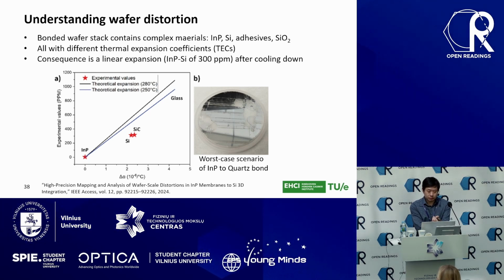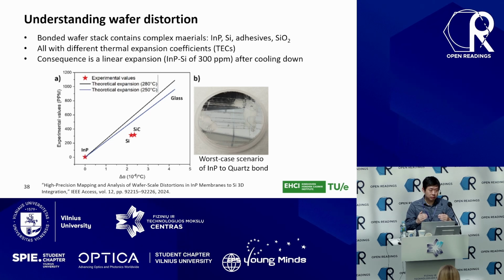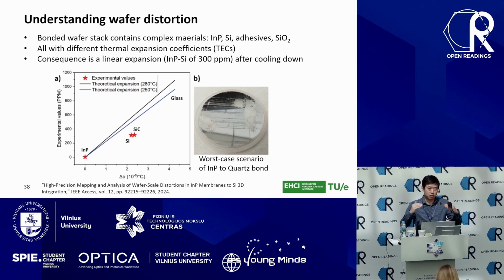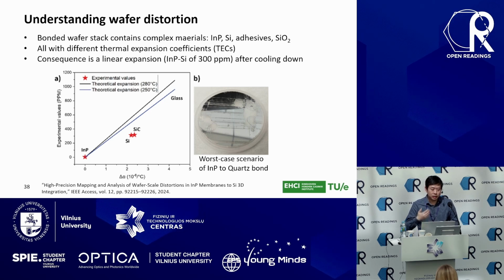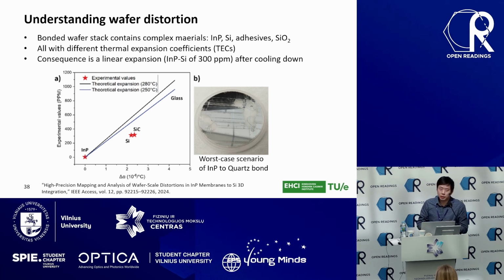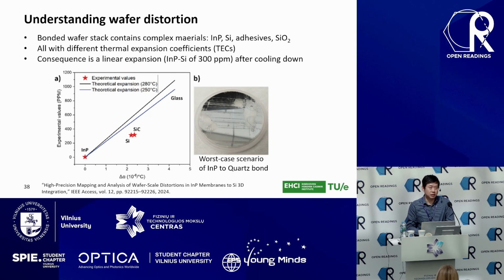So it means when the chip is cooled down to room temperature, the thermal expansion coefficient builds in, causing strain and deform the indium phosphide membrane on top, right? So actually the entire membrane experiences a linear expansion because of this. And some people may say, yeah, 300 ppm, it's 300 parts per million. It's a tiny value, right?